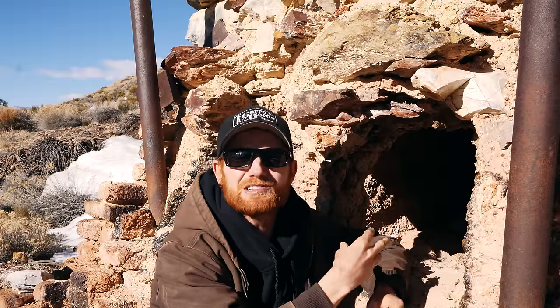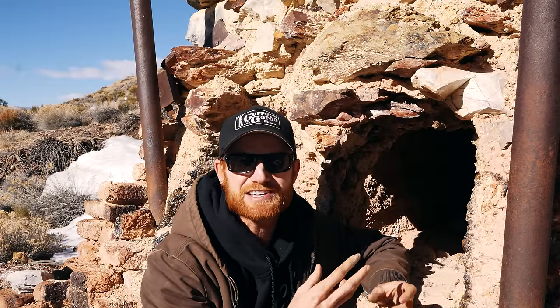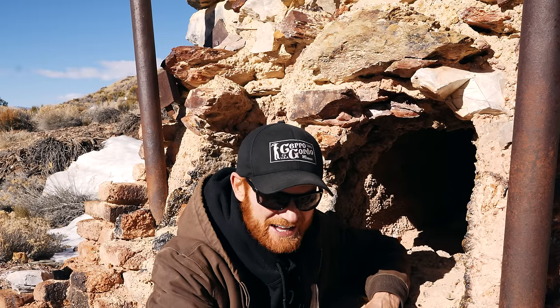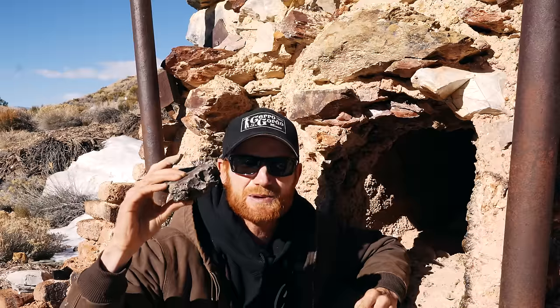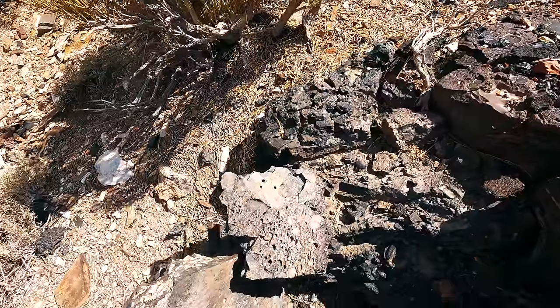After they had this whole mix, they would put it in the furnace with about 40 pounds of charcoal. And as the article states, the molten lead carries with it all the other precious minerals. So basically the heavy things, the lead, the silver, everything else, would be tapped off into this one area, and eventually you'd be left with just the lead and silver at the bottom, and on the top you have a little crust, just about maybe this much, that would be called slag, that you could break off, and this would hold all the impurities that you didn't want.